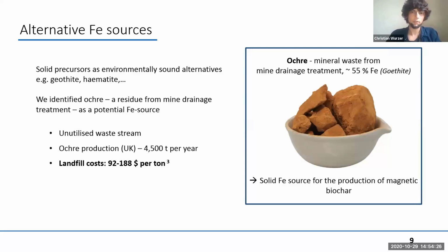So ochre is produced by draining abandoned coal mines. So underground coal mines, you have to remove the water from rainfall and groundwater influx to keep the structure of a mine stable. So you pump water out, and this is usually mixed with minerals. So you end up with an ochre sludge, which you have to dispose of. And in the UK, this is around 4,500 tons per year of dry sludge. You can see that on the right. So that's the ochre that I used to produce my biochar.